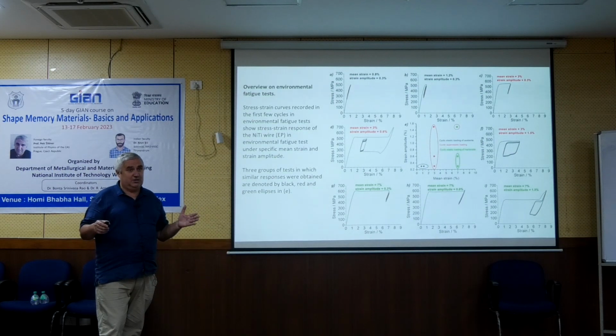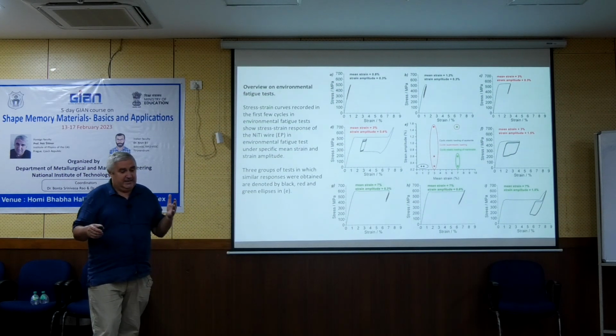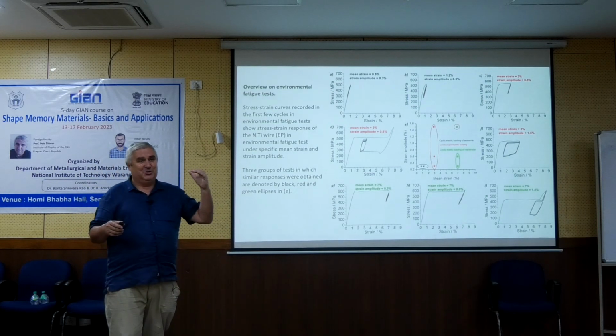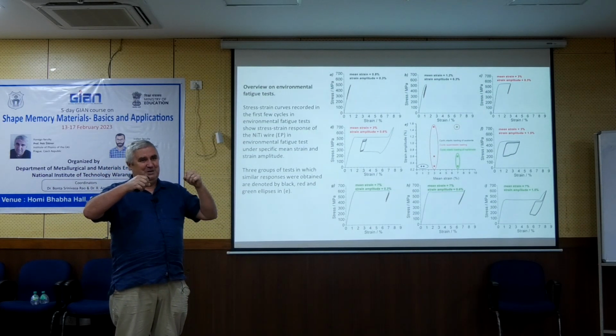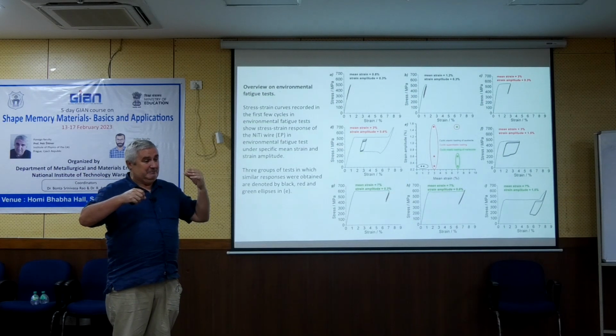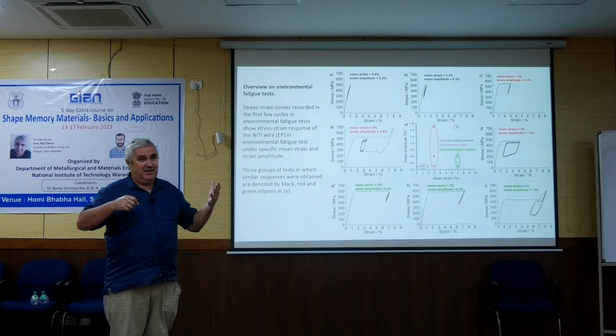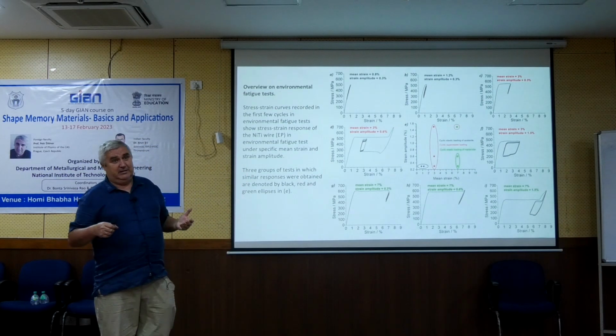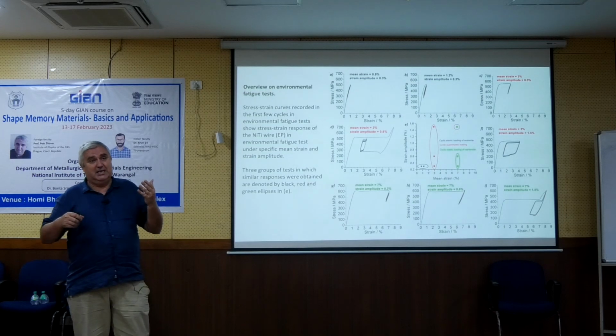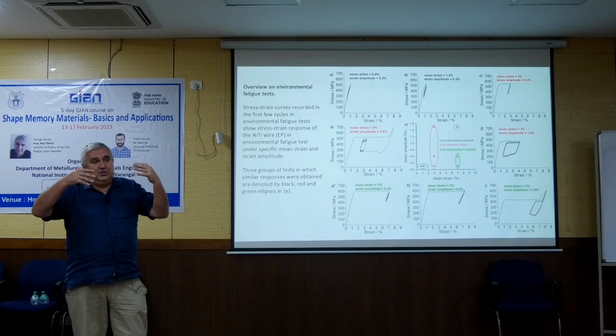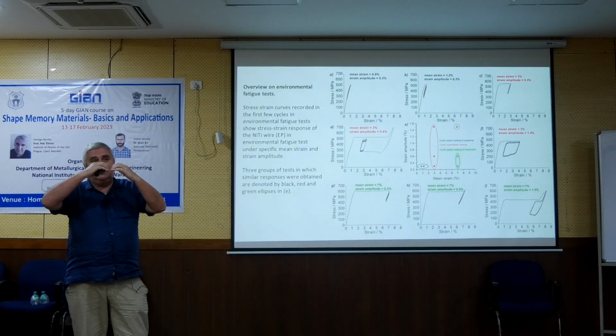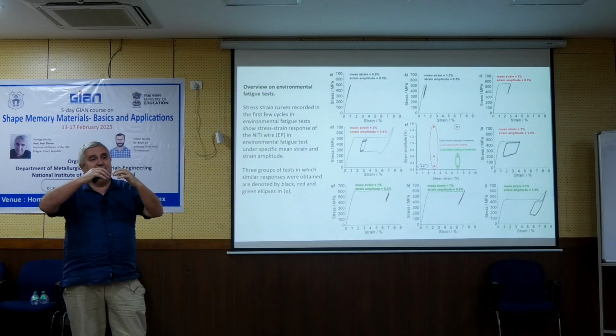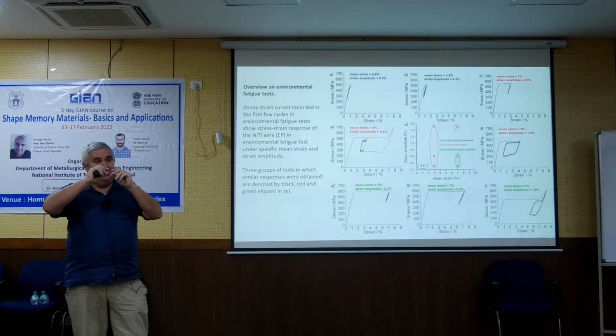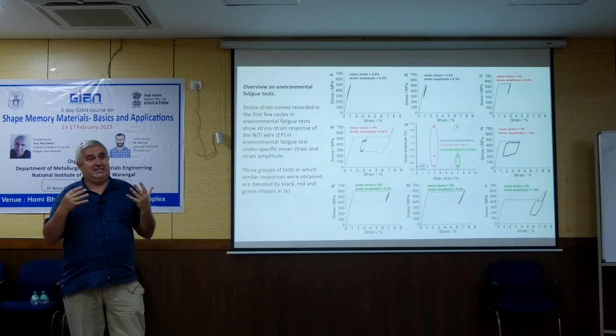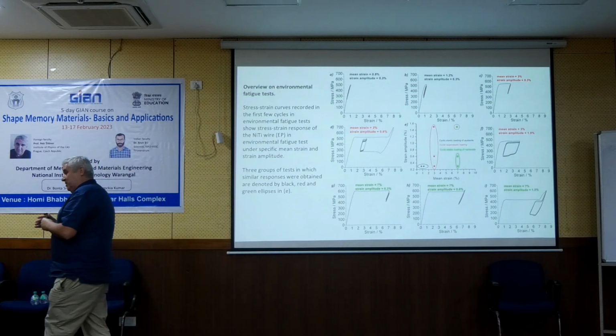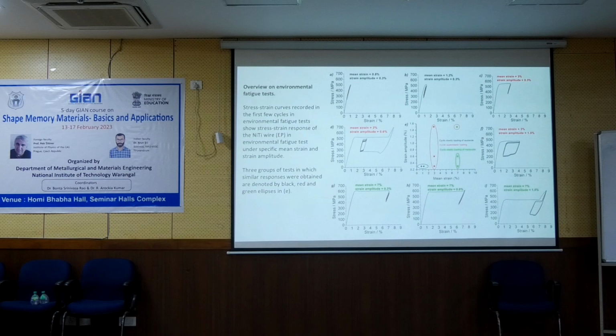So the wire which had no oxide, I say no, but there was some oxide. Our measurements show some kind of damage, but it cannot be seen in SEM. It can only be seen by this electrochemical measurement. The beauty of this measurement is that you cycle the wire, and what you see are nano-sized cracks on the surface. The measurement is only sensitive to the few nanometers on the surface. So for me this is exciting because you have access to something which is not available with my electron microscopy.